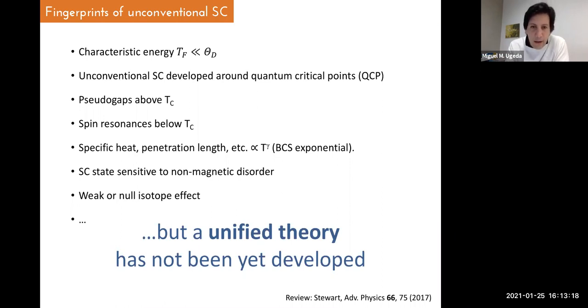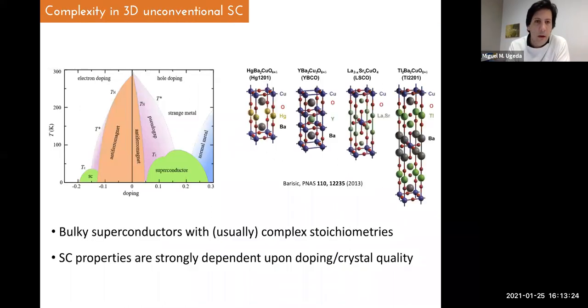And one of the reasons why we know little about unconventional superconductors, even though they were discovered 40 years ago, is, in my opinion, the enormous complexity of these materials. In particular, due to a couple of things. One of them is that these materials in bulk, in general, show really complex stoichiometries. For example, you can see this cuprate superconductor, where the unit cell is quite large and involves a lot of atoms with different elements, and that's quite difficult, for example, to model or to grow for an experimentalist.